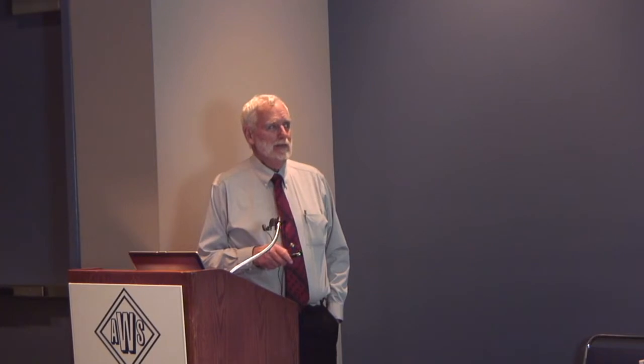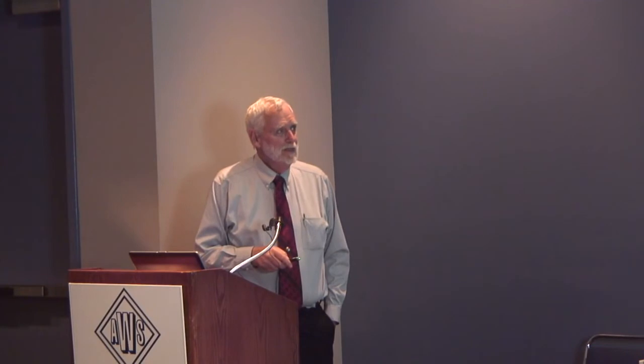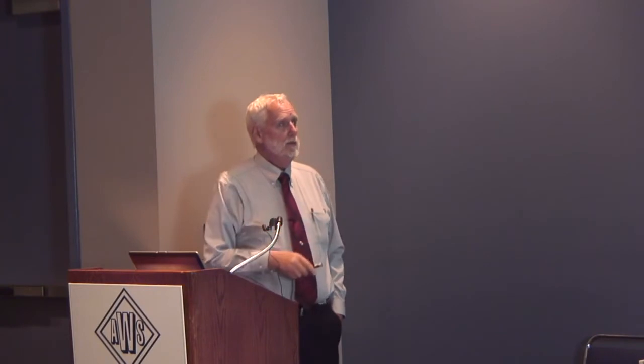When the weld metal melts onto the base metal, which is right here, there's your fusion line right there, it always grabs onto an existing grain, and it says, oh, I like to grow in that grain, preferential grain growth. And that's why these will always be attached. If you look real careful, they're always attached. For some reason, this one attached down here, and they attach onto a non-melted grain, and they grow. And they usually grow to the heat. Usually, they always curve to the heat source. This is right close to the top, and you don't see it.